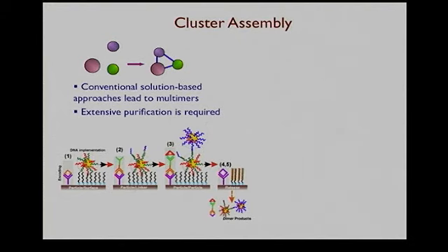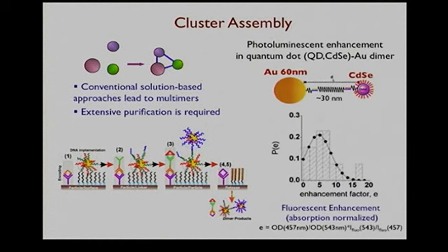So what I wanted to emphasize here is that it's a quite simple approach which allows us to get 75% yield without any purification. In this particular case, we can make it from gold or from silver, and they can be useful both from an optical perspective as well as from a biodetection perspective. But probably the most exciting is really to make a structure which contains two particles, not one metallic and one semiconductor. One is a gold particle, while another one is semiconductor cadmium selenide.